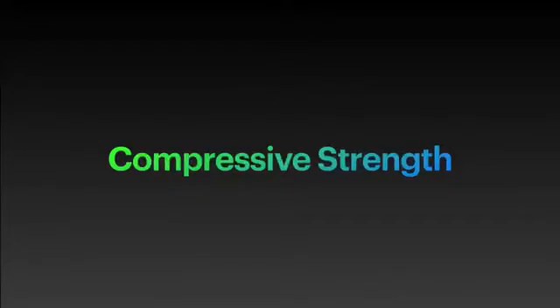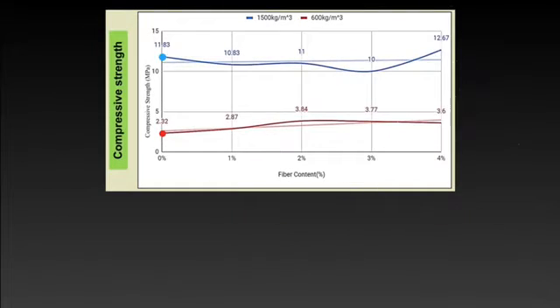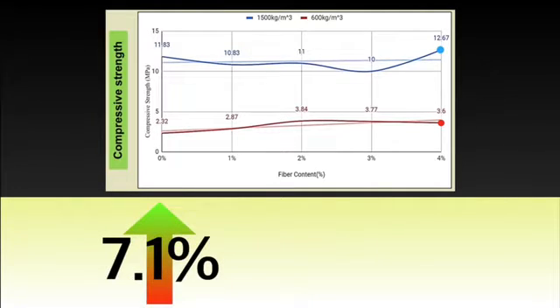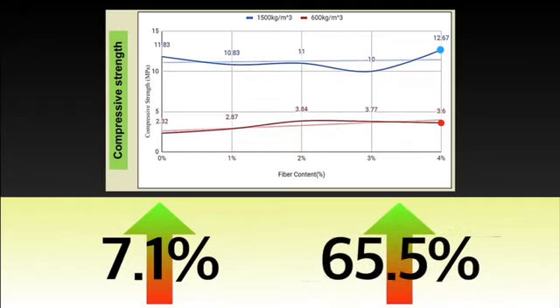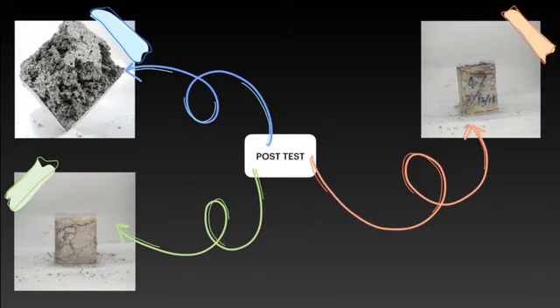First, compressive strength. For high-density Pulpcrete, a 7.1% increment is observed when compared to non-reinforced foam concrete. As for low-density Pulpcrete, a 65.5% increment is observed when compared to low-density normal non-reinforced foam concrete. Compressive strength means that more force is needed to force Pulpcrete to reach its initial failure mode.